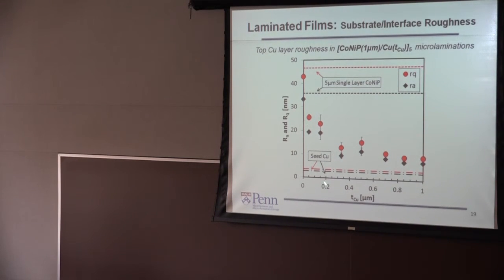As you can see, when the interlayer thickness increases, the roughness decreases and plateaus. It's bound by two limiting scenarios, the 5 micron single layer cobalt nickel phosphorus and the seed layer. So there are two conclusions you can draw from this plot. The 5 micron single layer has the highest roughness, as expected. There is no planarization effect. And increasing the copper layer has an increasing planarization effect to smooth out the surface towards the roughness of the seed layer.